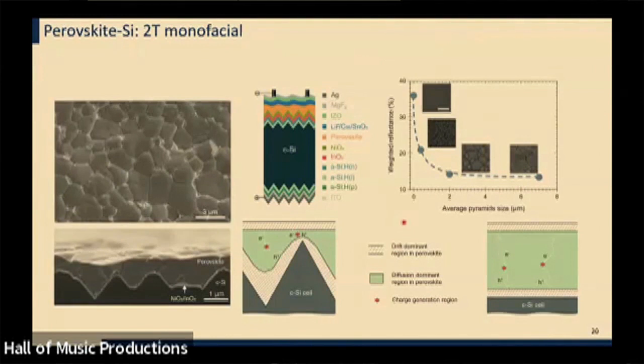Now, silicon solar cells actually have this great advantage, which is the beauty of the fact that we can etch silicon along certain crystal planes to make pyramids, which function as anti-reflection coatings. But if you're somebody trying to put a perovskite active layer onto one of these rough topologies, it actually comes as a challenge. And so in this study, we worked with colleagues to first figure out how could we keep the pyramids very optically effective at their anti-reflection job, but also make them compatible with the solution processing of the perovskite active layer.